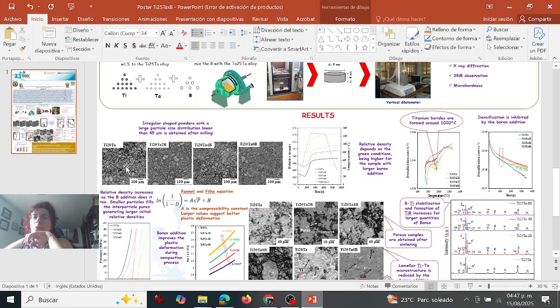And what we can observe is that we have irregular shaped powders with a large particle size distribution lower than 45 micrometers, and this was obtained after the milling.